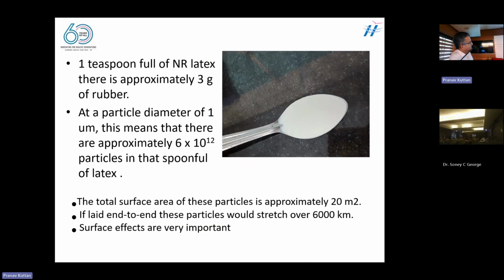So for comparison, in 1 teaspoonful of natural latex, there is approximately 3 grams of rubber. So you know that the total weight is much more than that. The remaining weight is water. So at a particle diameter of 1 micrometer, this means that it contains approximately 6 × 10¹² particles of rubber in the spoonful of latex.